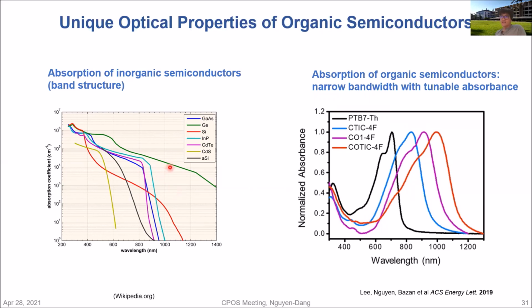On the left-hand side here, you have inorganic semiconductor, and you have the band-like structure. So the absorption coefficient depends on the wavelength in the way that, at long wavelength, you have low absorption. And when you have a photon with higher energy than the gap, you will jump up and you will have a plateau, or it just increases. So basically, you will have a sharp transition at a certain wavelength. For example, here for cadmium telluride, you have a very sharp transition. Whereas in this organic semiconductor, you have a very narrow bandwidth of absorption, with tunable absorption.